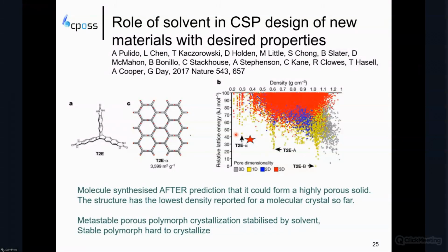And the one they were after here was metastable in the CSP. It did indeed have the lowest density reported for a molecular crystal at that stage. And its formation was because it was stabilized by all the solvents in the pores. So it did crystallize out. And indeed, finding the most stable crystal structure, which is also the densest, proved to be very hard to crystallize and only came out after they'd published the Nature paper on this.